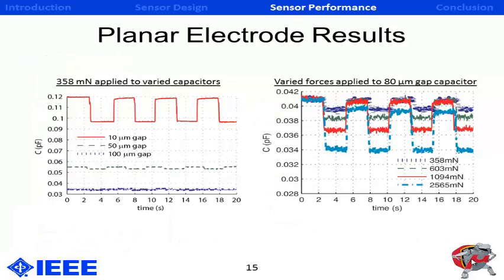A few additional tests were also done in the time domain. On the left-hand side, there's a plot of capacitance as a function of time, again for those 3 gaps. And as expected, we found the largest change in capacitance for the 10 micron gap. And it's interesting to note that the response time of the sensor was less than 0.1 seconds, which was actually probably a limitation of the analog-to-digital board that we used, which has a sampling rate of 90 hertz.